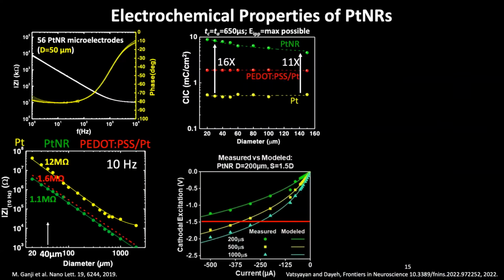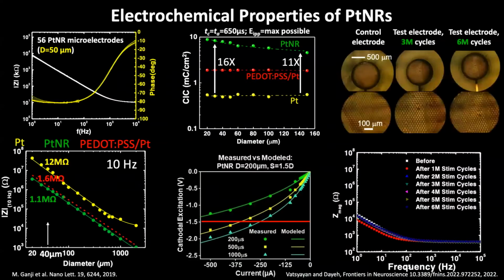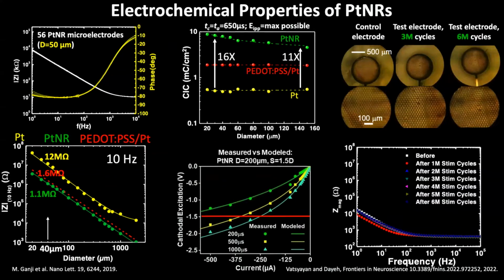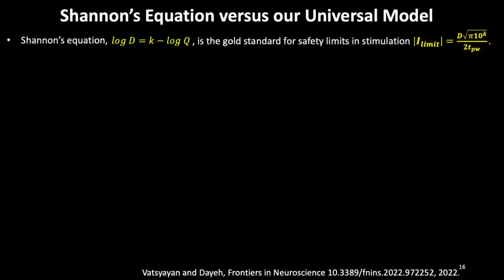So on top, now we see that charge injection capacity for platinum nanorods compared to PT, or platinum, again, over 1 order of magnitude higher than the planar contacts. You would also want to test the stability of these devices with millions of cycles, and the plot over here shows that their impedances are stable over a long duration of time.